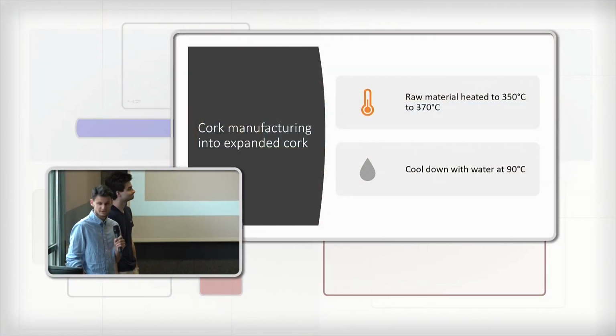The particularity of the bark from this oak is to have an external layer constituted by cells, which form a homogeneous tissue called cork. So what is cork? It's a complex mix of polymers. Every polymer in cork has intrinsic properties, and once they are combined, this gives cork. So to use cork for construction, it needs to be expanded. To do this, we need to heat the raw cork with water vapor. During the heating, the suberin, the main constituent of the cork, will act as a natural glue. Finally, the material is cooled down thanks to water at 90 degrees. We use this temperature to avoid thermal shock.